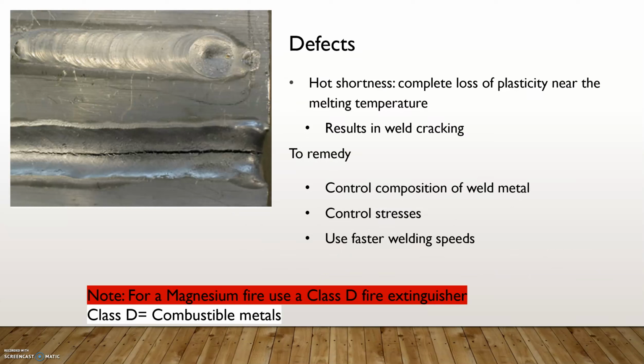A common defect is hot shortness, which is a loss of plasticity near the melting temperature, and this usually results in cracking. To control hot shortness, try and control weld metal composition, and you can reduce heat input by welding faster. A side note here that comes up on your test is that a Class D fire extinguisher is used for magnesium fires. Magnesium can combust in its dust form.